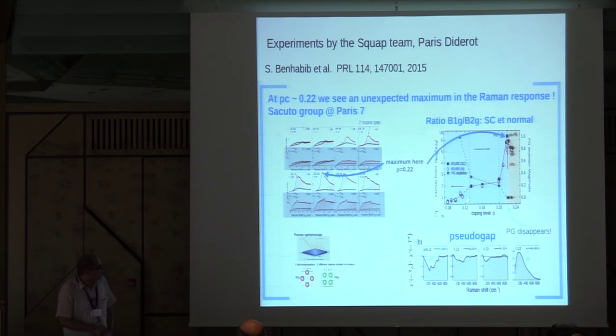All right? And they also can measure the loss of spectral weight. And this is the pseudogap. This white region is the loss of spectral weight. And the pseudogap decreasing. And they find this magic point where the pseudogap disappears and the Raman intensity is maximal. Okay, this is very unusual. What is very unusual is that the Raman intensity then decreases again. It should be increasing all the time, the Raman intensity. But this is not the case.